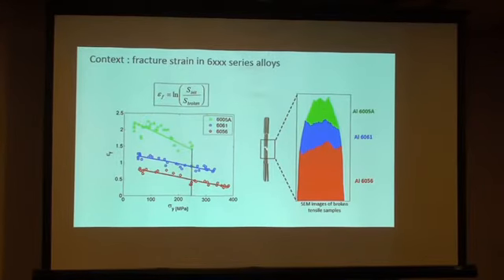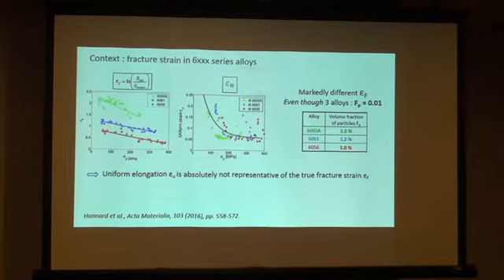And when you measure the fracture strain, so I'm really talking about the logarithmic ratio between areas at the beginning and at the end of the test, you see that there is a huge difference among these three alloys. A first typical explanation would be to say that the necking behavior is different. However, if you look at the uniform strain, I mean the strain at which the necking starts, you see that they follow the same trend. Another guess would be a difference of particle volume fraction. But if you look at the microstructure, you see that they all exhibit about 1% of particles.